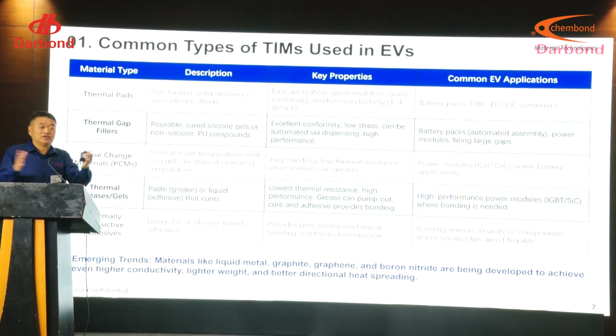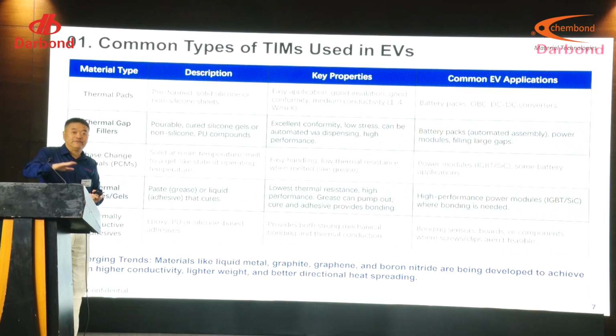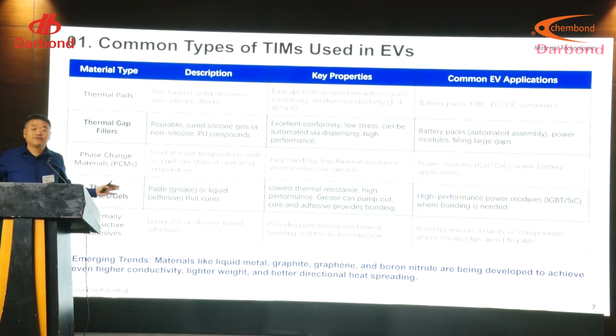For example, the pad: when you have a gap larger than 200 or 300 microns, you use the pad. That's the first generation. And later on, you can use the liquid because it has more conformity. Because a pad is usually a cured elastomer, you have high contact resistance. So liquid has the advantage, especially for different stack heights, since it has more conformity. Generally we say these two are gap fillers. These two, phase change and thermal grease, are usually used for the semiconductor die. Semiconductor die, yes.